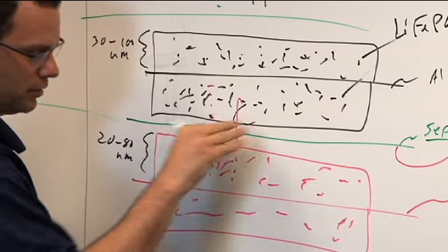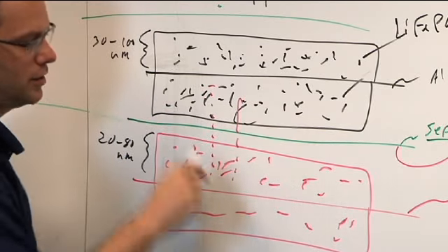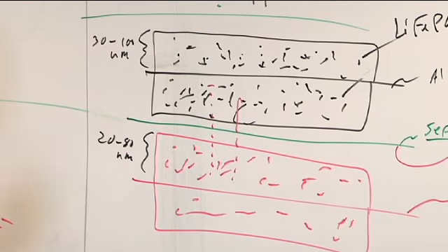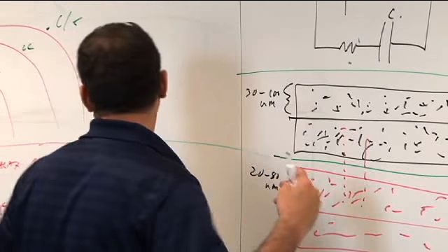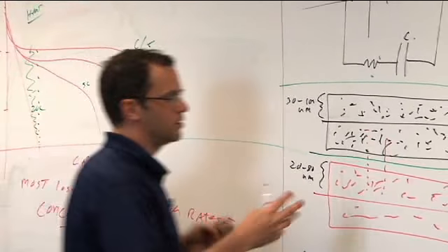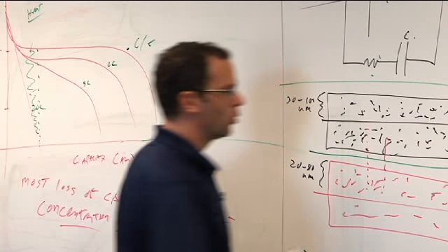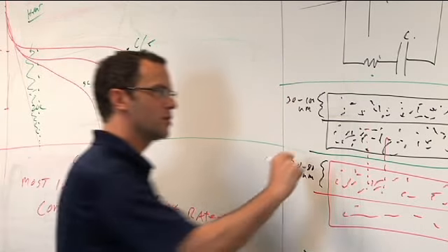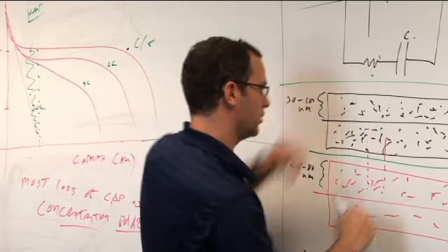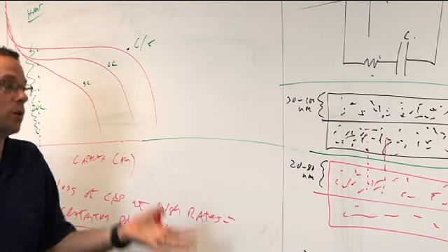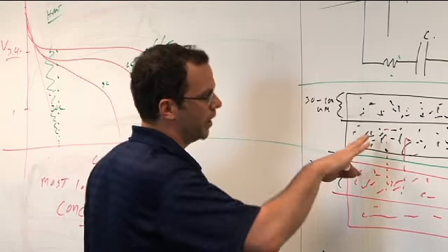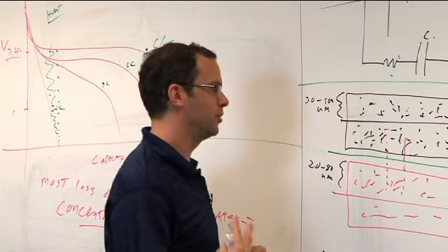We locally extract all the lithium that we can from the pore-filled electrolyte regions here, and concurrently, we cannot extract lithium fast enough from inside this structure. We become what's called locally starved of functional ions, okay? And this happens more rapidly the faster we ask the current to come. The point at which we lose capacity or lose functionality entirely is the point where we have a region somewhere within our battery where we're out of lithium ions. There's no longer lithium at some point in this cross-section of this single cell, and the function stops. There's no more capacity, okay? The more current we draw, the faster this occurs.